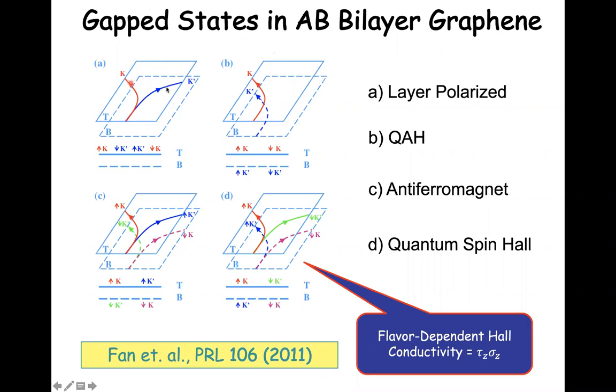So state A is a state in bilayer graphene that's easy to generate experimentally simply by applying an electric field. So you push electrons from one layer to the other so that they're mostly in the top layer. And so in this state, all of the states in both valleys are polarized to the top layer. But as indicated by these arrows, that actually means that they have opposite chirality, opposite Berry curvature, and opposite contribution to the Hall effect. So when the wave functions in the two valleys are polarized in the same way, then you don't get a net Hall effect. The Hall effects cancel.